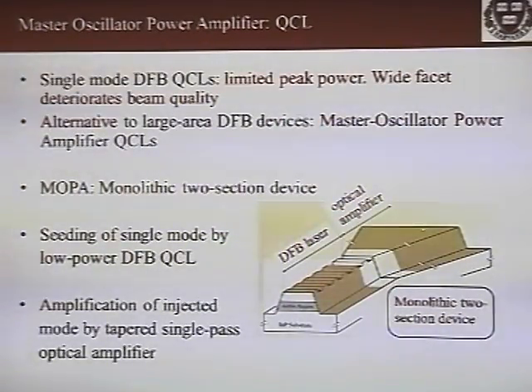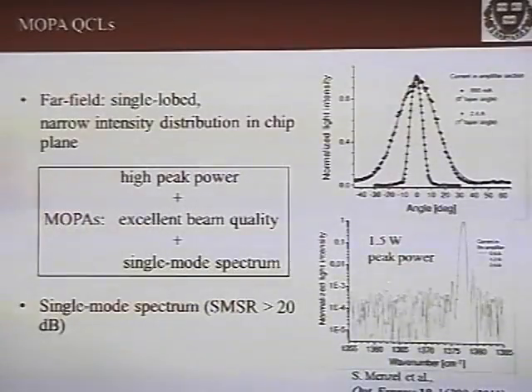So the idea, which is not a new one, we adapted it to QCL. If I now put an amplifier here, and of course I want to put an anti-reflection coating in here, so this stuff does not lase, okay, and I have an adiabatic taper. The fact that it expands gradually, you can maintain single mode, but now go to high power. And we were able to do it. This is recently published work. Look at the spectrum. This is a standard of telecom engineers that all the engineers know here. Single mode means that you have to put it on a log scale and you have to cut at least 20 dB, if not 30 dB. And so we were able to get 1.5 watt peak power, single longitudinal, single transverse mode.